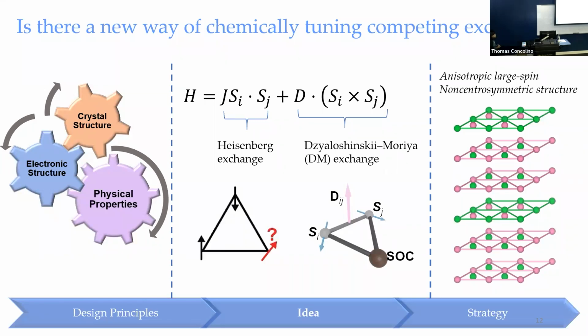And the way we approach our work is based on a very simple connection, right? It's crystal structure, electronic structure, and physical behavior. So the idea is that if we can modify the spin Hamiltonian, in addition to the Heisenberg exchange interaction, in this case for a triangular lattice, and if we also induce an anisotropic asymmetric exchange interaction, and we can make it a little more sizable, right? So that it can also compete with the Heisenberg exchange interactions.